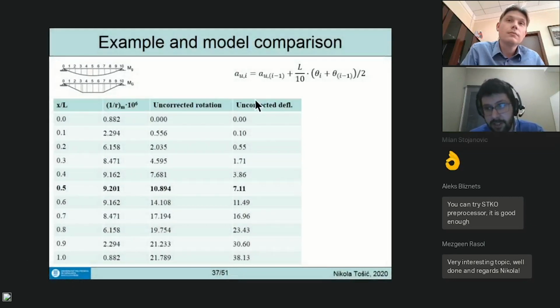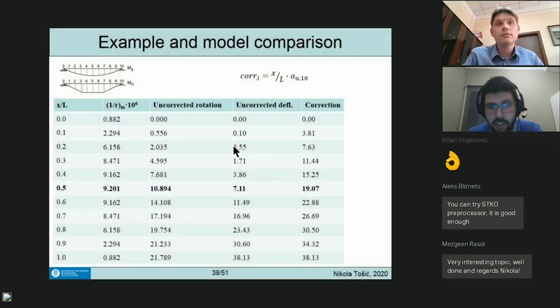After that, I do another integration to get uncorrected deflections. Again, this doesn't look good because the deflection is highest at the support. So I need to introduce a correction for the deflection, and it just means getting it to 0 at the end. So the correction is just going to be x over L times the last deflection. The correction here is going to be equal to this, so it's going to get it down to 0.